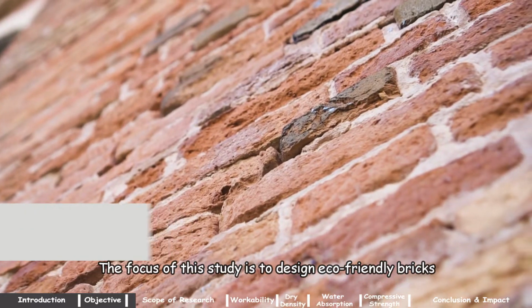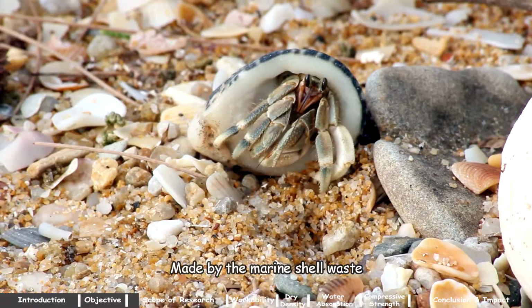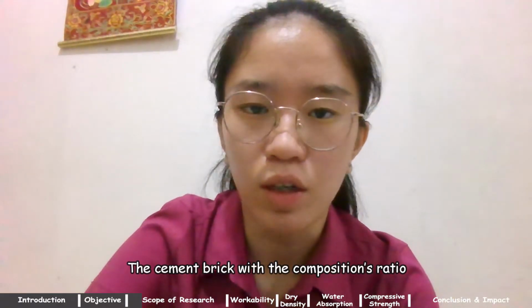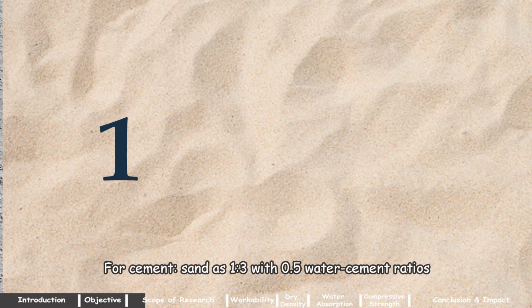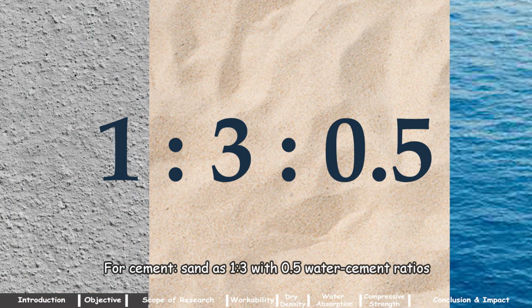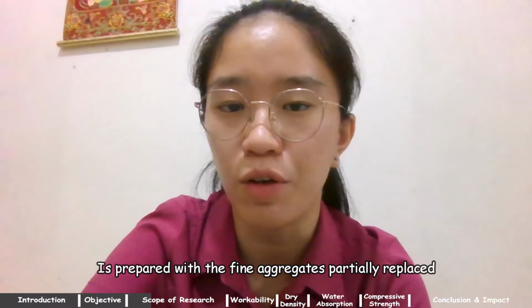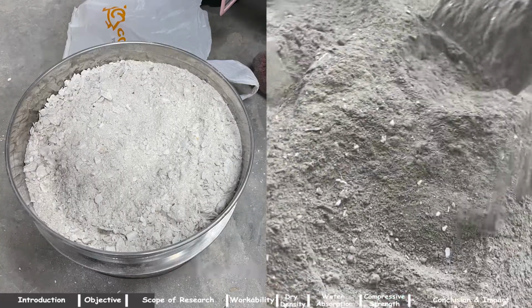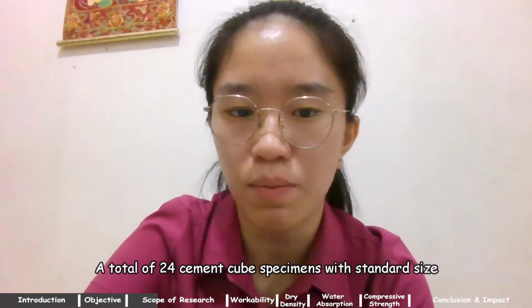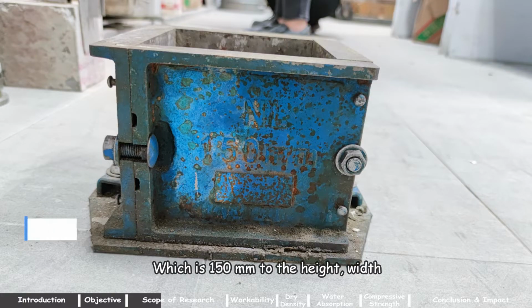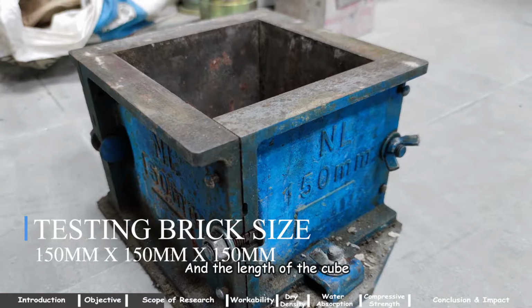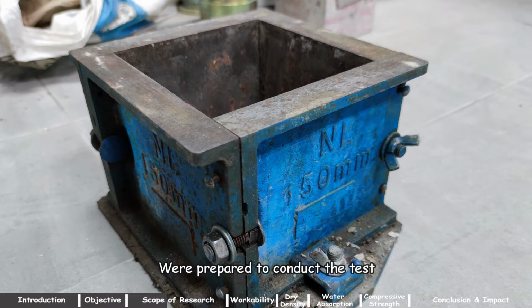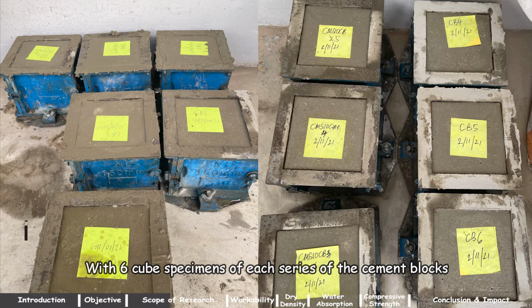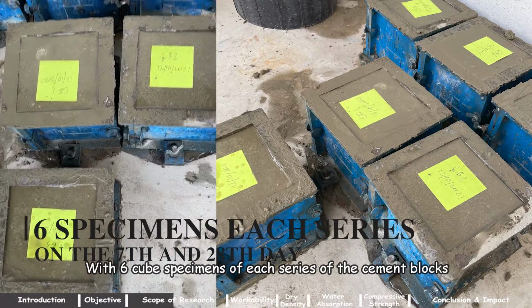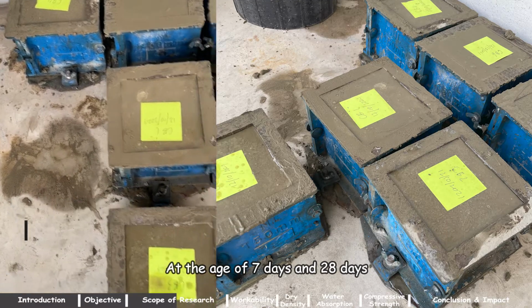Hello, I'm Karen Grade Suling. The focus of this study is to design eco-friendly brick made by the marine shell waste. The cement brick with the composition ratio for cement to sand as 1:3 with 0.5 water cement ratio is prepared with the fine aggregate partially replaced by the crushed marine shell. A total of 24 cement cube specimens with the standard size, which is 150 mm in height, width, and length of the cube, were prepared to conduct the test, with 6 cube specimens of each series of the cement block at the age of 7 days and 28 days.